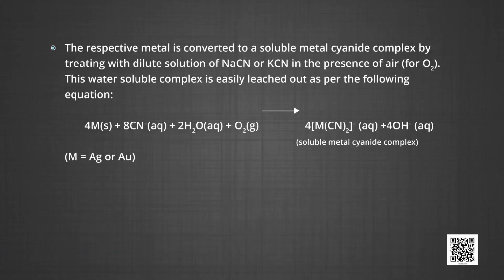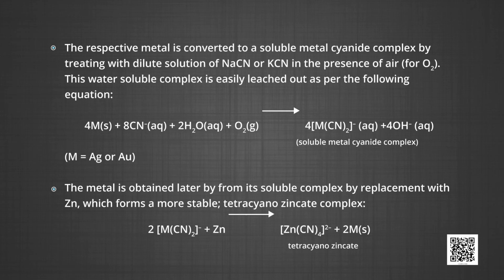Now, let us see the metallurgy of silver and gold by the process of leaching. In case of metallurgy of silver and gold, metal is recovered in the following steps. For the first step, the respective metal is converted to a soluble metal cyanide complex by treating with dilute solution of sodium cyanide or potassium cyanide in the presence of air or oxygen. This water soluble complex is easily leached out as soluble metal cyanide complex. Second step, the metal is obtained later from its soluble complex by replacement with zinc, which forms a more stable tetracyanozincate complex.